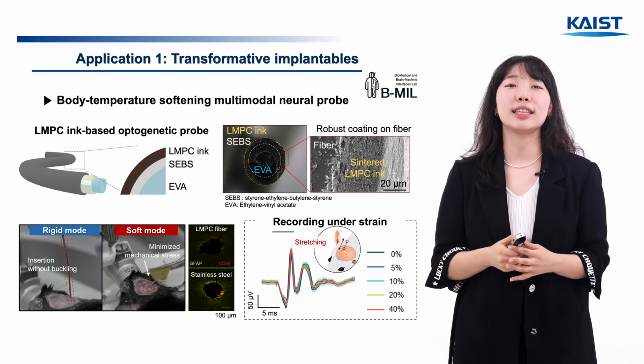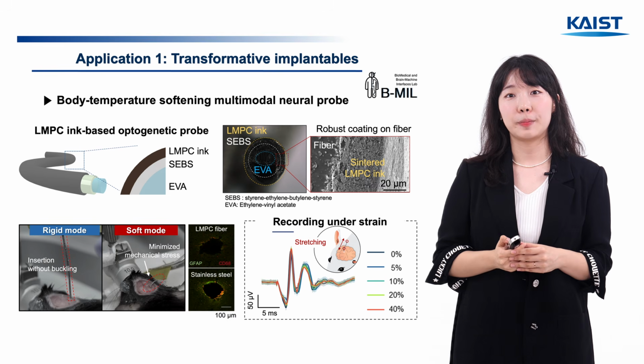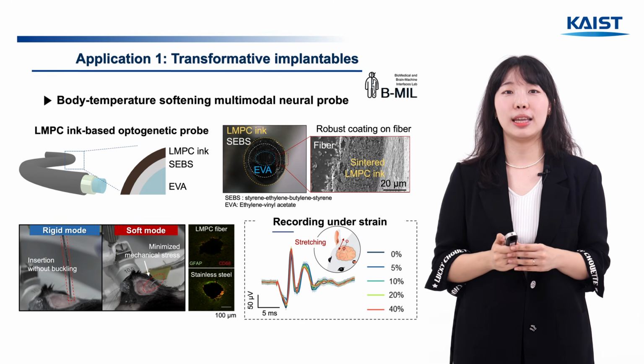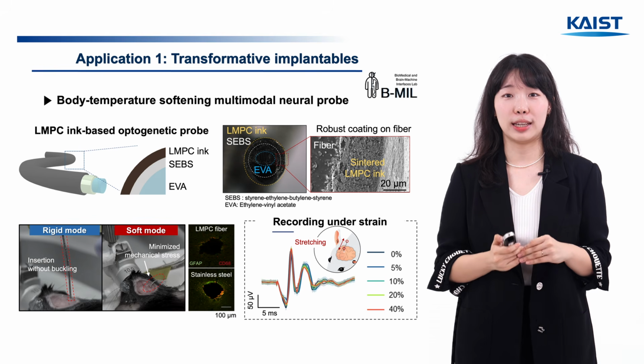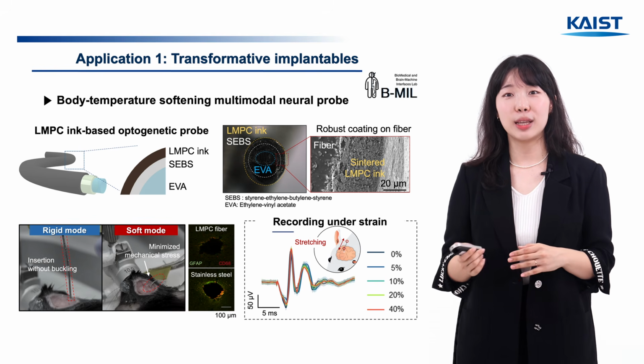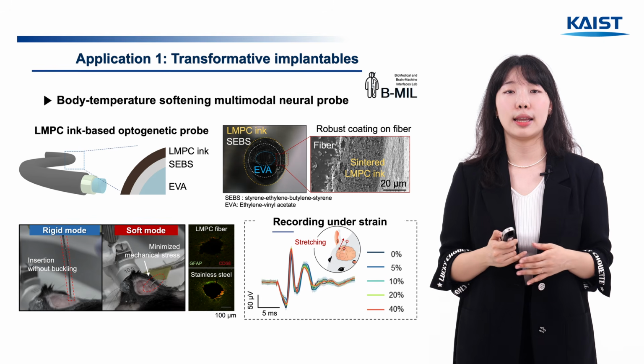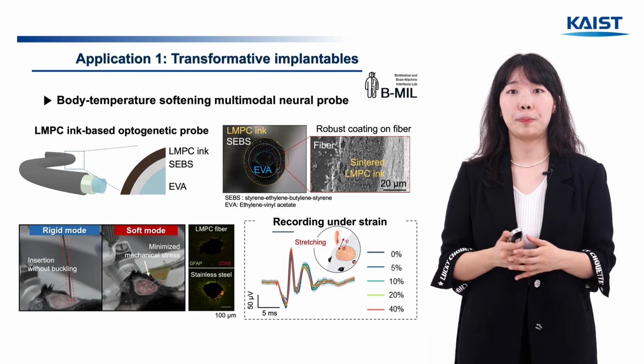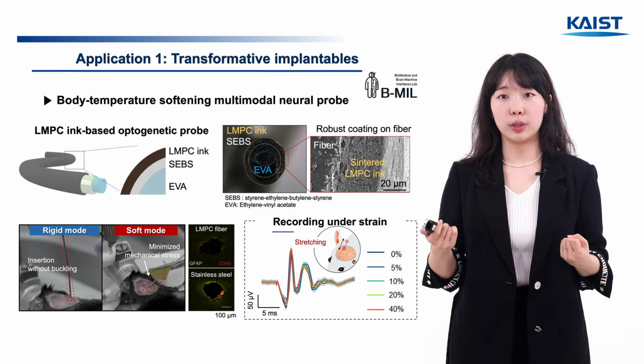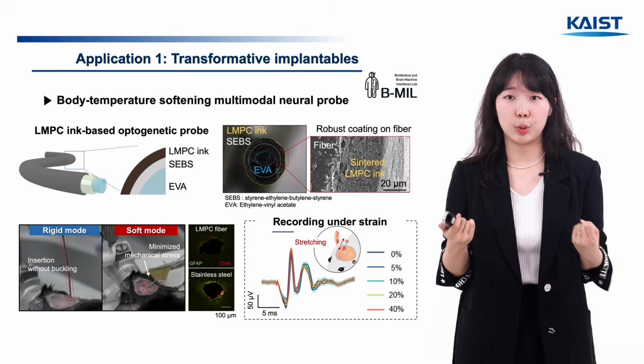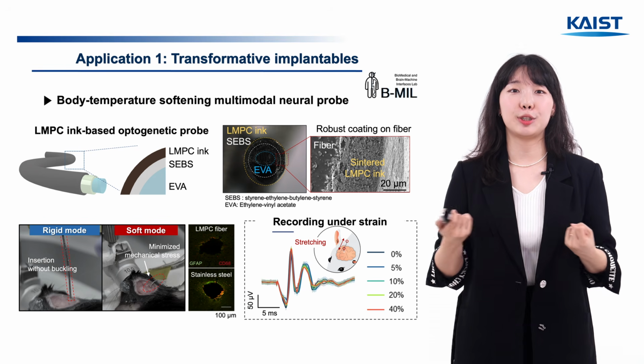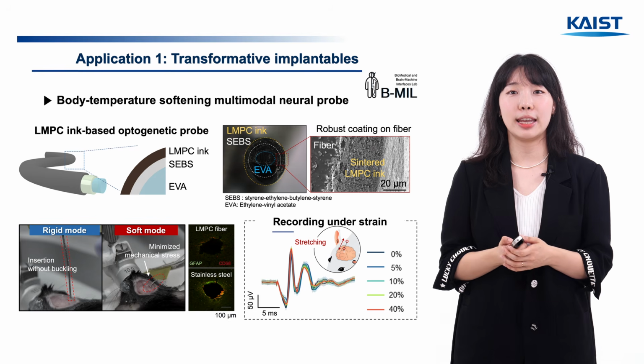We then inserted the actual probe into the rat's brain. In the rigid mode, it could be inserted stably to the target location, and in the soft mode, it showed less inflammation than a conventional stainless steel probe. And thanks to the soft mode, the probe could still measure brain signals reliably even when stretched.